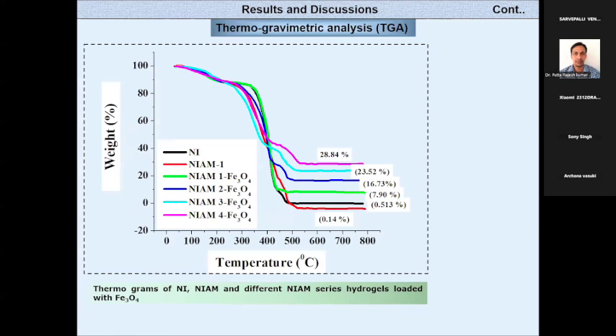How much percentage of nanoparticles is formed inside of the hydrogels, that you can also confirm by thermogravimetric analysis. Ultimately, if you reach a certain extent, for example, every hydrogel has a certain equilibrium position. If it is absorbing 100% water, it will absorb only 100%. If the polymer capacity is 150 grams of water, it will absorb only 150. Some threshold value is there. So here also, the formation of nanoparticles will have some threshold. Beyond that, however much iron ions you are incorporating into the hydrogel, it will not form. Am I audible?